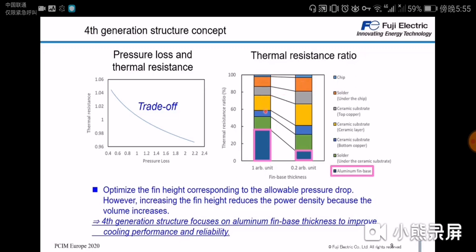Gray, yellow and blue are showing the ceramic substrate itself, with the top copper layer, the ceramic material and the bottom copper layer. Then in green we have the solder between the ceramic substrate and the aluminium fin base. And here in blue we show the aluminium fin base itself.